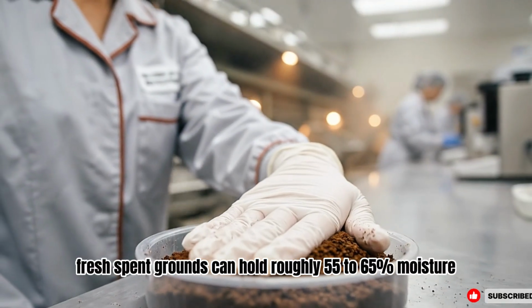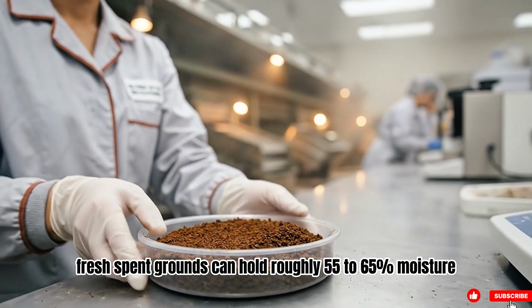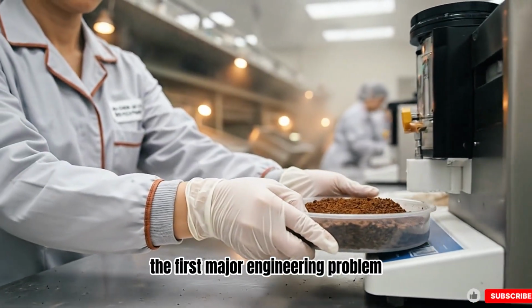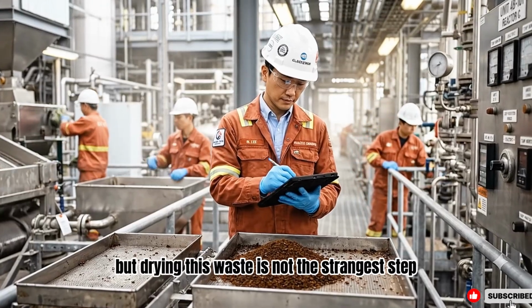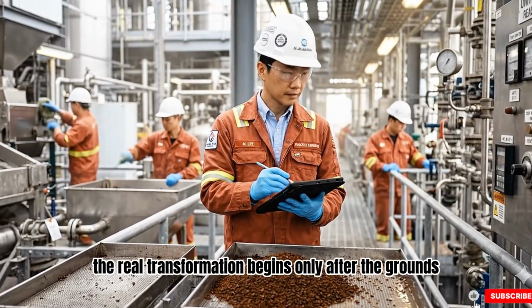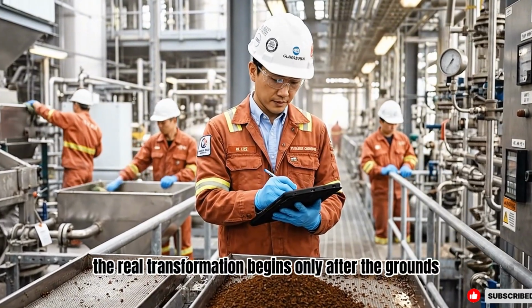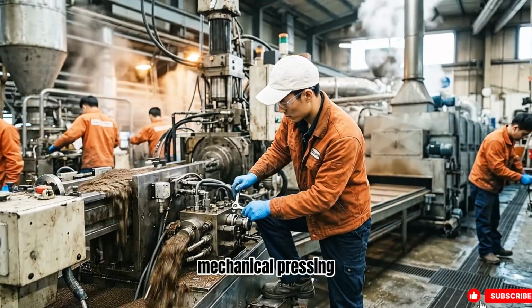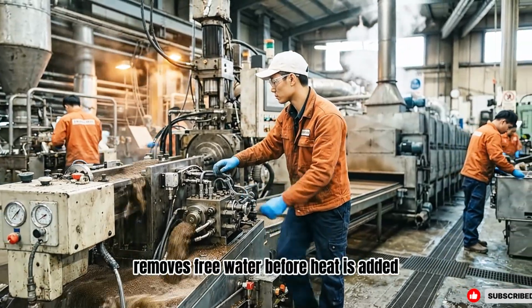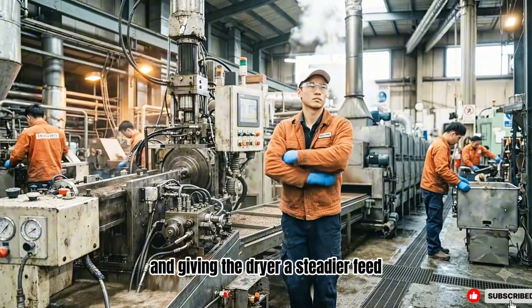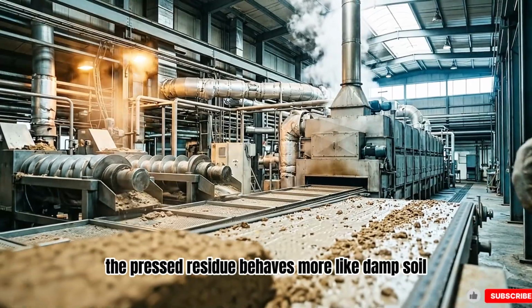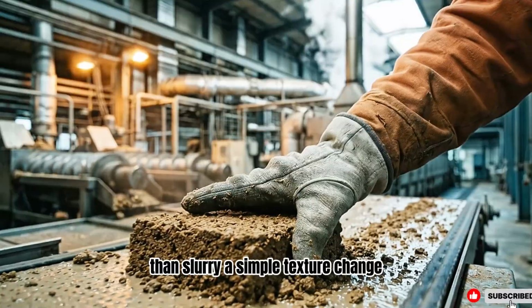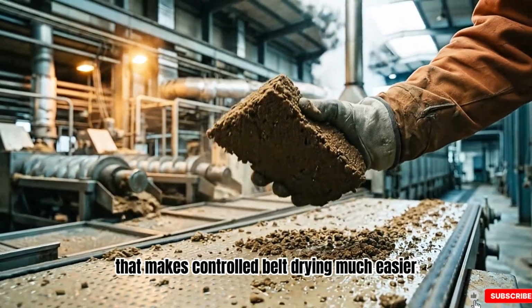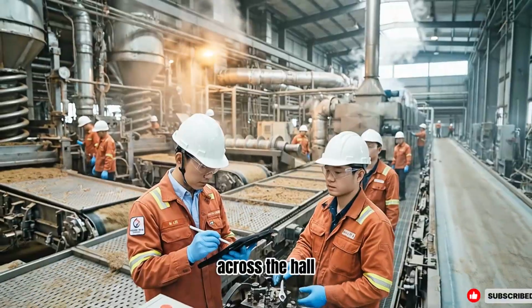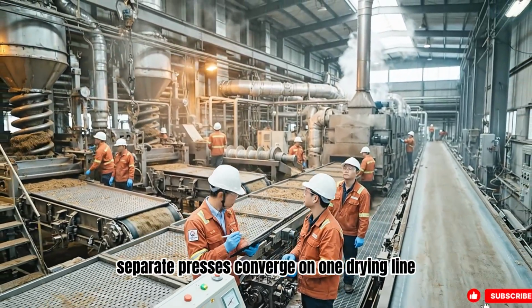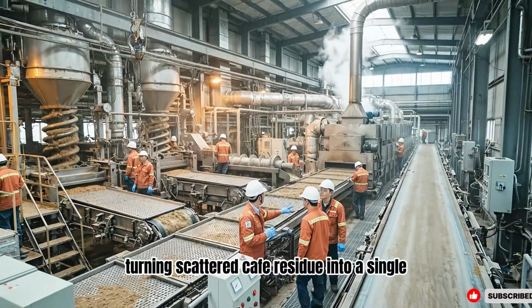Fresh spent grounds can hold roughly 55 to 65% moisture, making water removal the first major engineering problem. But drying this waste is not the strangest step. The real transformation begins only after the grounds become a controlled powder. Mechanical pressing removes free water before heat is added, reducing the energy needed later and giving the dryer a steadier feed. The pressed residue behaves more like damp soil than slurry, a simple texture change that makes controlled belt drying much easier. Across the hall, separate presses converge on one drying line, turning scattered café residue into a single continuous